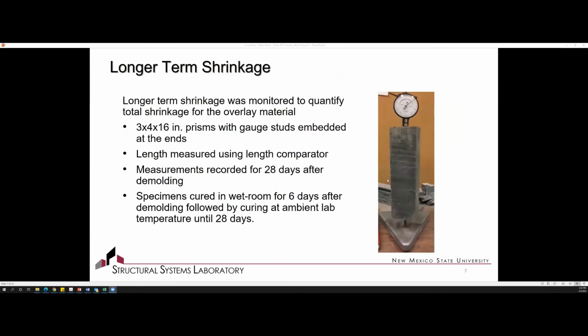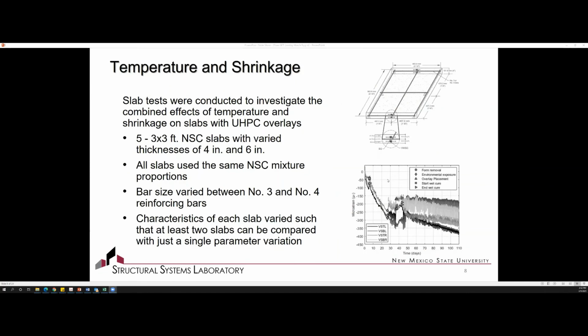We also looked at a little bit longer term shrinkage. Again, looking at prisms, we took length measurements for up to 28 days after demolding. So we have a little bit of an idea of what goes on in the longer term as well. Then we also wanted to double check and look into the temperature and shrinkage effects, or the combined effects of these. So we conducted some slab tests.